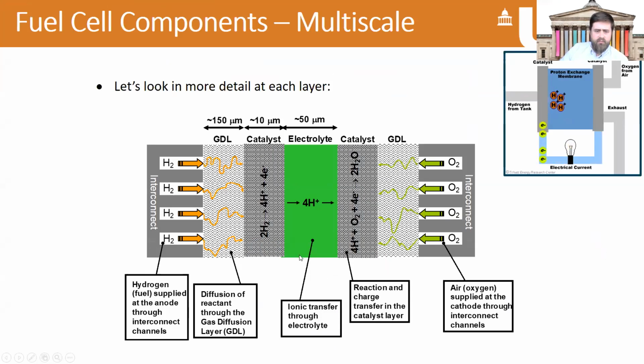As I say, there's lots of different material challenges and lots of actually different science that occurs on different length scales in order for this to happen. Okay, so the very coarse length scale, we've got flow channels of about 1 millimeter here in the current collectors, and that supplies the gas. Then we're going down to sort of length scales of 150 micron thick gas diffusion layers with fibers that are about 10 to 15 microns in size. Then the catalyst layer has very small particles of carbon on it, around 100 to 300 nanometers, and they have even smaller metallic nanoparticles of catalyst on there, which will be less than 10 nanometers and actually less than 5 nanometers in most cases in terms of modern catalysts.